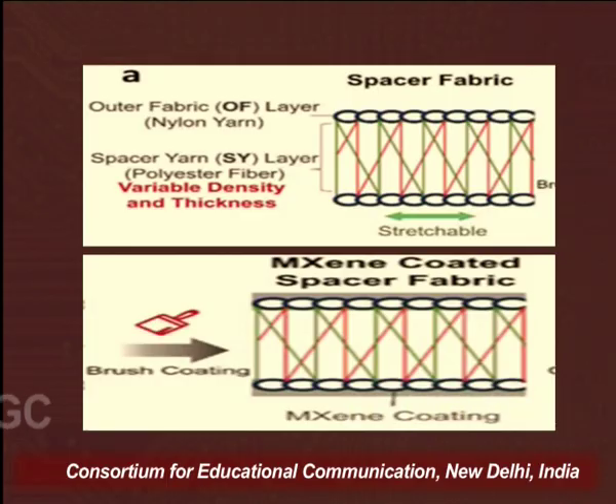So, presenting the compressive stress strain curve of the spacer fabric with the different SY structures, offering the unique compressive characteristics and different hysteresis. So, maximum stress at the 65% compressive strain was achieved for all spacer fabric with increased spacer threading with different distances, signifying the importance of increasing SY yarn threading for high stiffness.